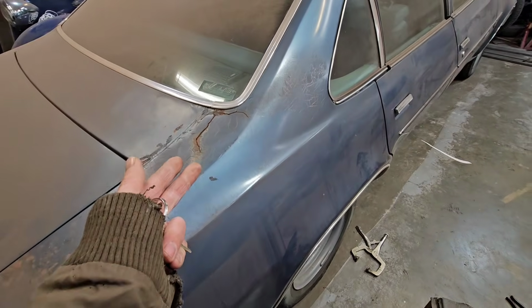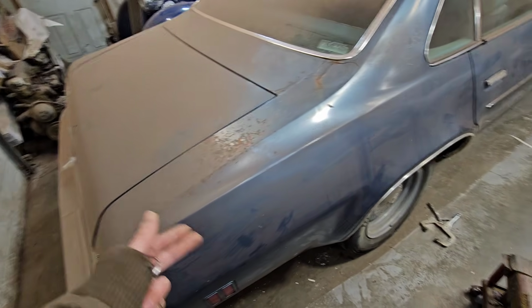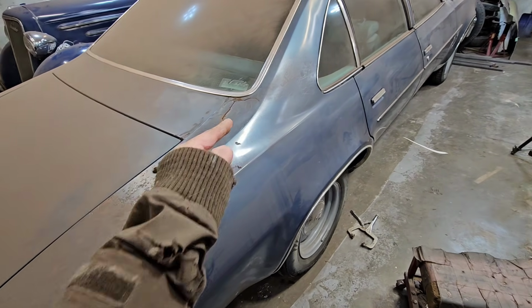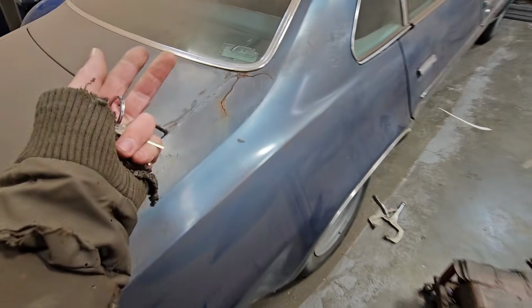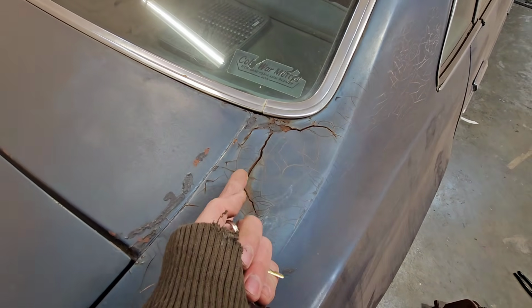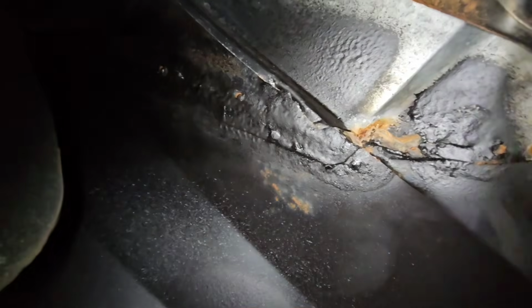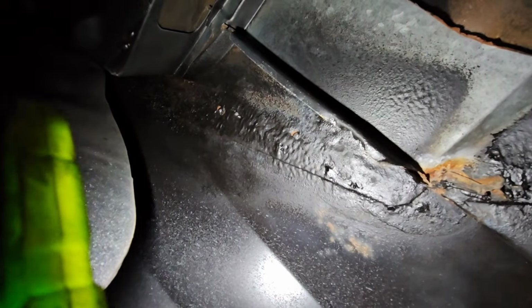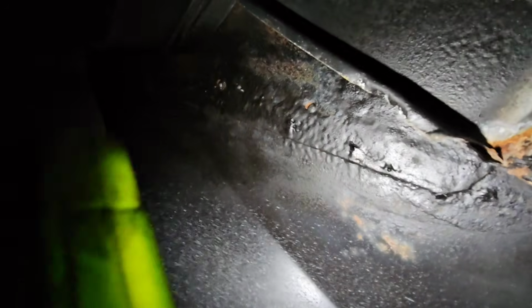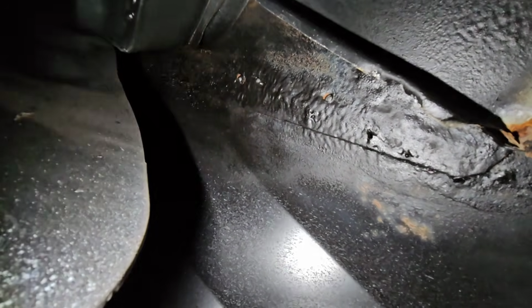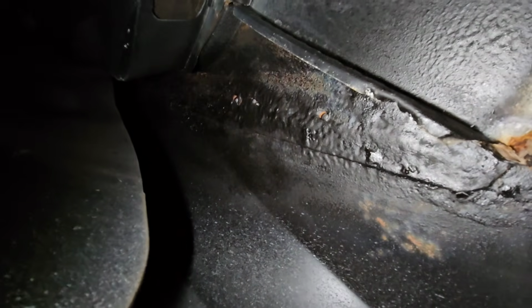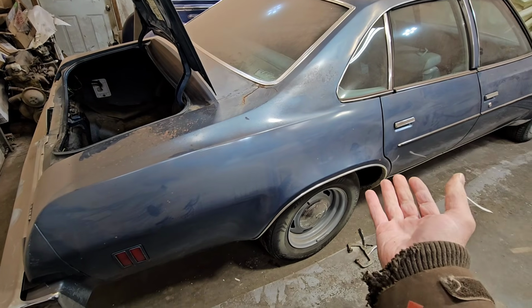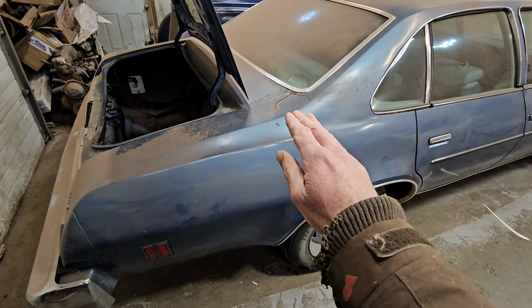This is the way that things were done by body shops 40, 50 years ago. This was considered acceptable, and this would have been a good repair at the time, but you can see it has not stood the test of time very well. Here's a look from inside the trunk here, and we can see that lap welded seam that was done by the body shop. And again, by the standards of the time, this was actually a good repair. You can see that they actually did try and seal it up from the backside. But regardless of all that, the seam still has failed. Of course, the quarter panel still hasn't fallen off yet. So structurally, yes. Cosmetically, failure.